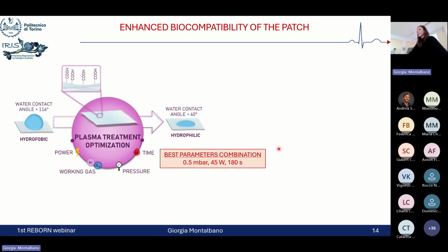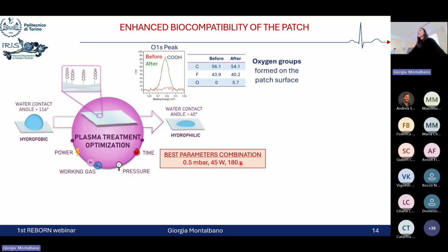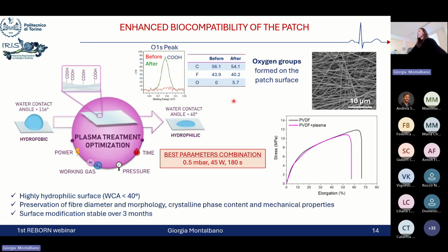So in the end, after this very large assessment, we defined the best combination of parameters represented by high pressure values, low power levels, and longer exposure times, where the effectiveness of our treatment was immediately confirmed by XPS analysis that detected the formation of oxygen groups on the surface of the patches compared to the non-treated samples. Moreover, the characterization of the samples also further confirmed the effectiveness of the treatment, registering a significant drop in the water contact angle of the surface, reaching values lower than 40 degrees.